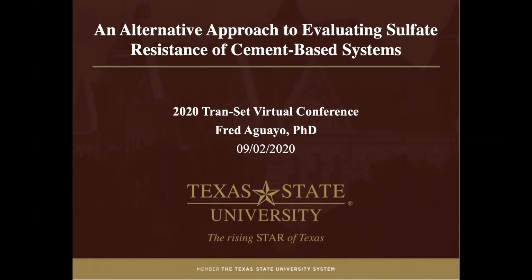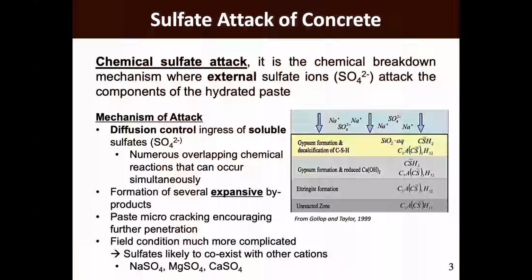It's basically looking at a new sulfate resistance test method that we developed in our lab about 2 years ago. If no one in this room is familiar with it, sulfate attack, in this case chemical sulfate attack, is when sulfates external to the concrete ingress and cause deterioration. Typically, this is in the form of expansion, cracking, and spalling on the surface. And this could be really,